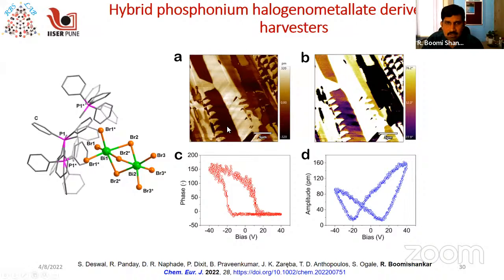We can also use the tip of the PFM to visualize the ferroelectric and piezoelectric properties. For example, you can record the phase changes. This shows a 180-degree phase change, which means that the signals are flipped. For example, if the polarization at this point is like this, at this point it will be like this. The butterfly-shaped loop is characteristic of a piezoelectric material. That comes from the amplitude changes, and this is the phase change. These two graphs are related to each other, whereas these two graphs are related to each other. This is at a single point of this strip, whereas you are able to visualize about 5 micrometers of the surface in this particular measurement.